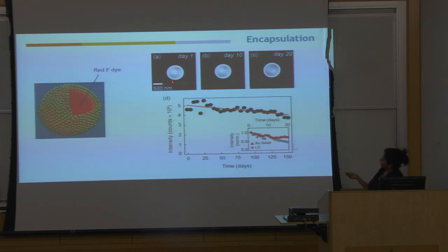We monitored the intensity of the dye over a long period of time, because now we are putting things in a shell whose wall is not actually solid. It's made out of nanoparticles, closely packed, but still it's like a porous shell. Chances are this thing would leak out, but if you look at the intensity, there's very little change. It encapsulates the dye really well. And we looked at the dye intensity for about 5 months, and there's very little loss of the total dye inside.